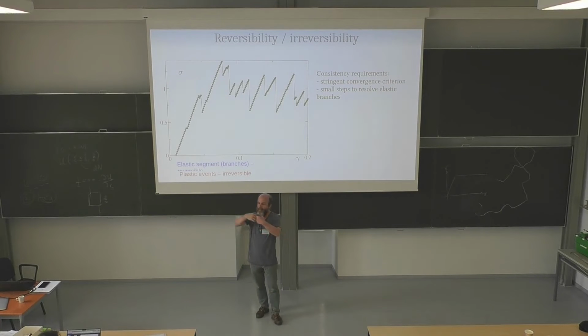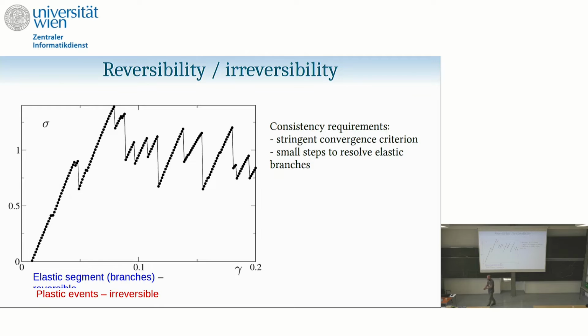You have plastic events that release energy, and this energy triggers some vibration of the system, which has eventually to be dissipated, and eventually it is dissipated by viscosity. But the rate of energy release is just the size of the jumps. And this is uniquely fixed by the potential energy landscape and by nothing else. So, not by friction, just fixed by the structure of the potential energy landscape.